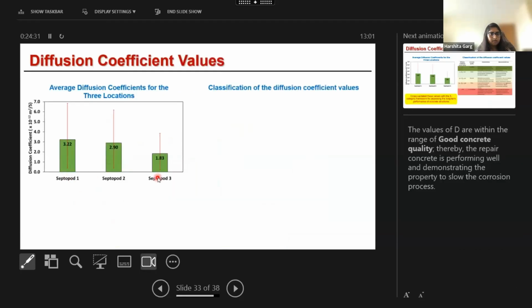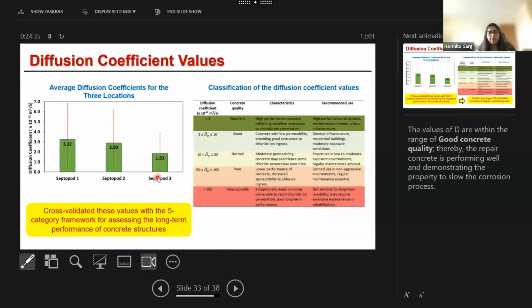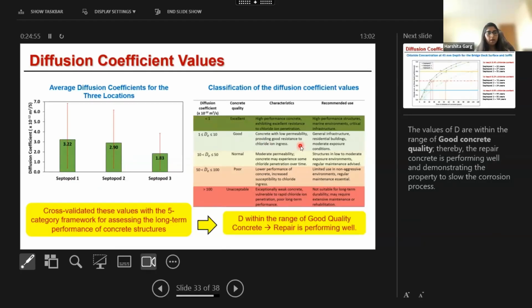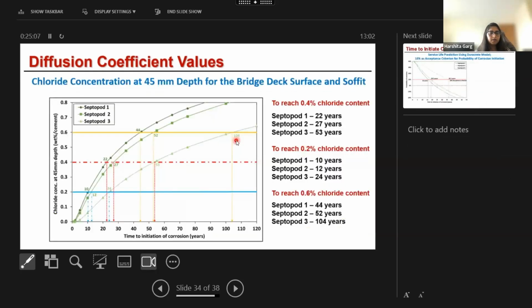On comparing these 3 values with the 5 category framework for assessing the long-term performance of concrete structures, we can see that it lies in the second one, which is good quality concrete providing good resistance to chloride ion ingress. So this is further qualitative information that we have got from the analysis. Now, these values can be used in any service life model for service life prediction. Here I have used this in DuraCrete modeling to predict the time taken to initiate corrosion.